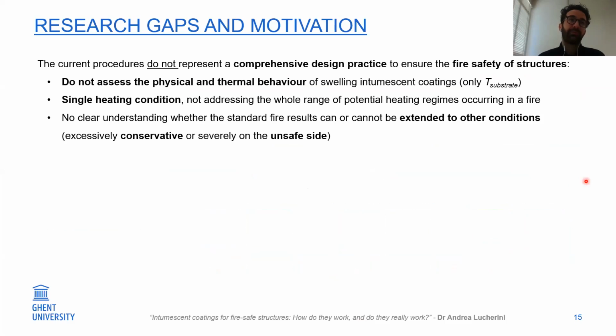And what I see as a problem is that the current procedures don't represent a comprehensive design practice to ensure the fire safety of structures. So they don't assess the physical and thermal behavior of intumescent coatings. They only look into the temperature of the substrate. They're based on a single heating condition. So they don't address, for example, a range of potential heating conditions that might occur in a fire. And also from the literature, you can see that there is no clear understanding whether the standard fire resistance test results can or cannot be extended to other conditions, because sometimes they are excessively on the conservative side and sometimes they are severely on the unsafe side.